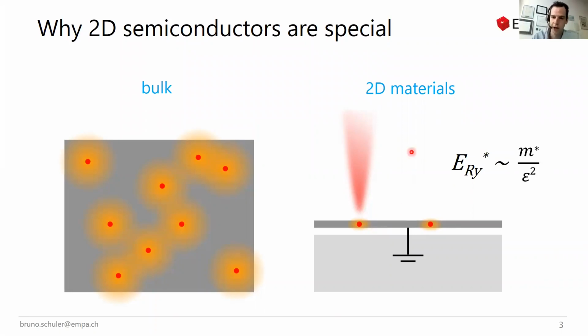Now, there is another cool aspect about 2D materials, and this is that you can tune them over quite a big range, for instance, by electrostatic gating or by changing the substrate. So they are quite flexible in terms of how you can tune them by external means. Also, they form very nice interfaces with other materials. For instance, in many 2D or van der Waals materials you don't have lattice matching requirements. So we can grow these things epitaxially on each other without needing the same lattice constant, and that's something which is different in bulk semiconductors.